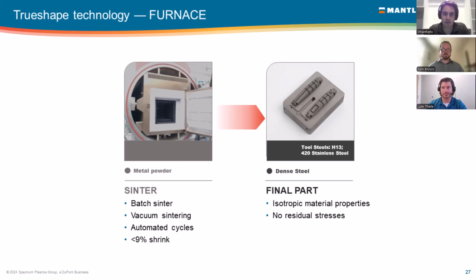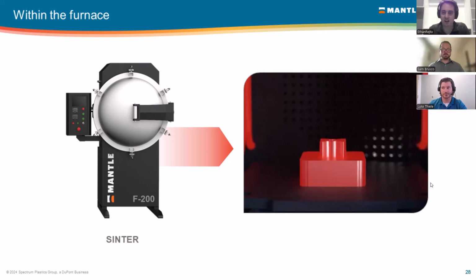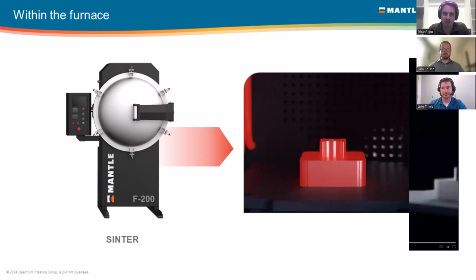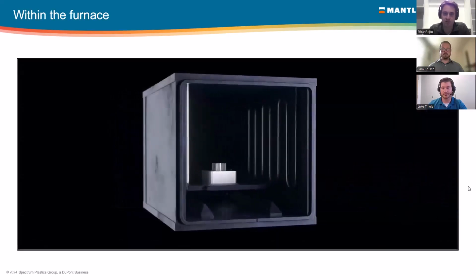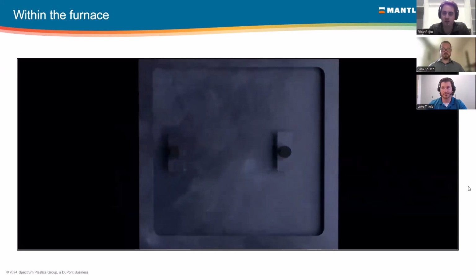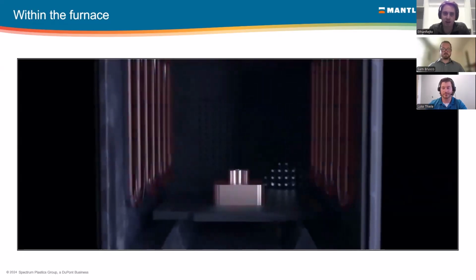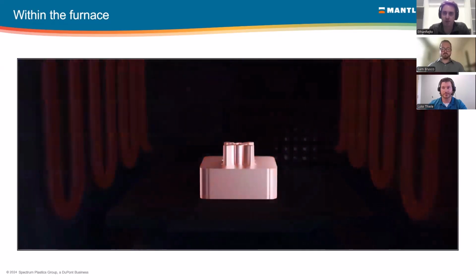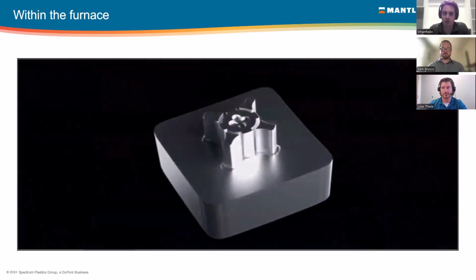You can see on the next slide, it's a little harder to get a camera into a high temperature furnace, but I have a video here showing some of the sintering process. You're simply placing the part into this furnace. You close it up. This takes 36 to 42 hours. It gets hot. The material shrinks about 9% and it densifies into a dense, strong steel component.